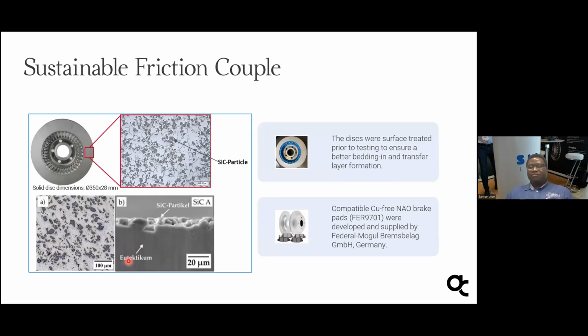Now back to the disc itself, the material itself. Here you can see this is a disc. It's a solid disc used for the test, and here is the microstructure. You have the aluminum alloy reinforced with silicon carbide particles, as you can see in the structure.